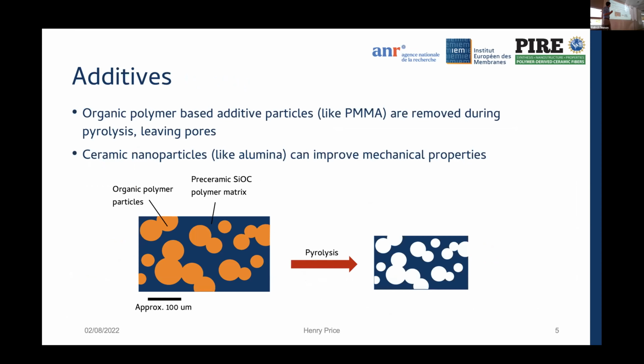So now the additives I used. One of them was PMMA, and the purpose of adding PMMA is as a sacrificial filler during pyrolysis. PMMA is an organic polymer, and so at the heightened temperatures of the pyrolysis process, it will be removed. This diagram shows the general theory and goal of this project, which was to suspend these PMMA beads in a printed part. I'd add them to the resin, it would be printed, and have these beads suspended in the actual printed part. Now, during pyrolysis, these beads would be removed, leaving behind cavities, which in theory could be manipulated to create some kind of interconnected porosity with end goals in membrane applications.